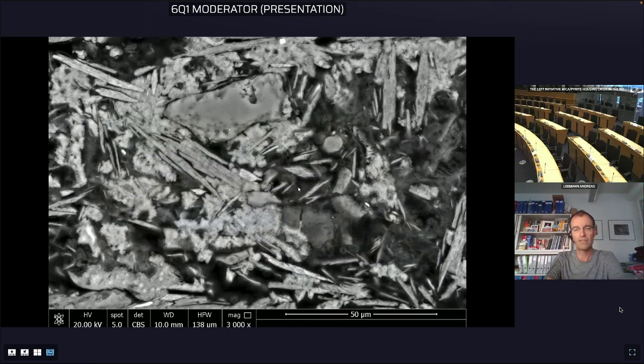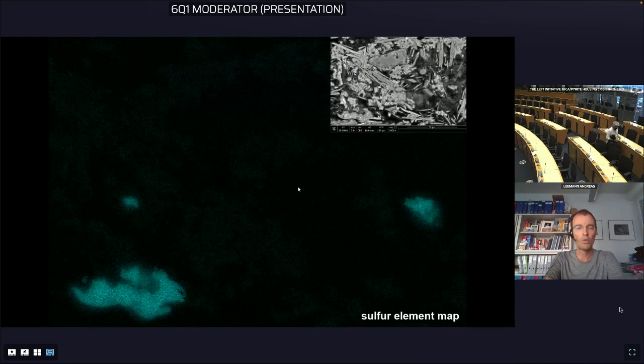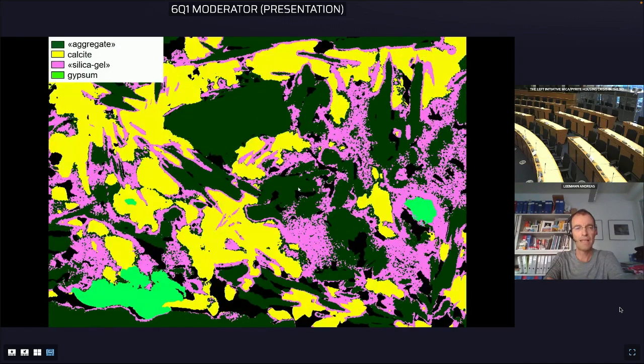Back to the concrete. This is a section of cement paste. Again, we do the sulfur mapping. Next, please. Now you see only 3 spots that have this blue color, which means where the sulfur is. Again, a phase map is done. Next, please. So again, dark green the aggregate, yellow the calcite, pink the silica gel, both products of carbonation, and green the gypsum, the only witness that is left from what has happened before. Next, please.